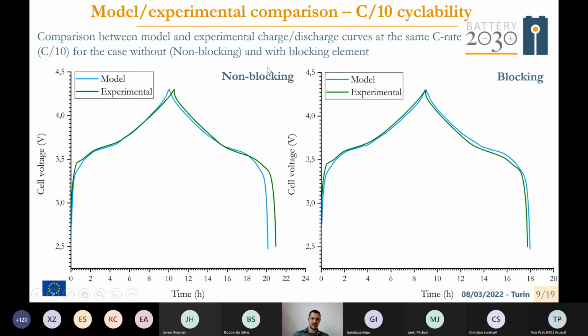As you can see, in the left panel are the experimental and model results for the non-blocking situation, and to the right for the blocking situation. You can observe an effective reduction in the charge-discharge times in the blocking situation compared to the non-blocking one, due to the interfering effect of the element on the lithium ion flow from the electrodes.